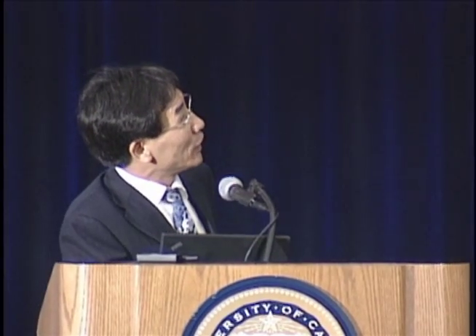And maybe we can collaborate with the Chancellor's group. We can make a superconducting film on top of the topological insulator by using molecular beam epitaxy. He also mentioned this iron-based superconductor. So we already obtained quite good materials of iron selenide on top of the graphene.